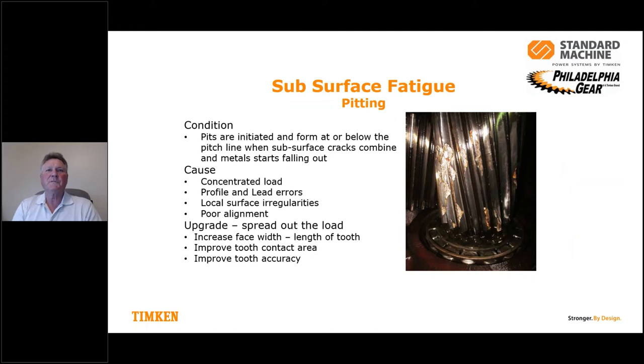So subsurface fatigue, which we also refer to as pitting. What's the condition? Pits are generally initiated and form at or below the pitch line. The pitch line is basically where the two mating gears would theoretically mate when they make contact. They're really subsurface cracks that combine, and as they combine and move to the surface, the metal starts falling out. The cause can be a number of things. One is a really high concentrated load in one area, which creates fatigue in the gear tooth. Profile and lead error is very common.